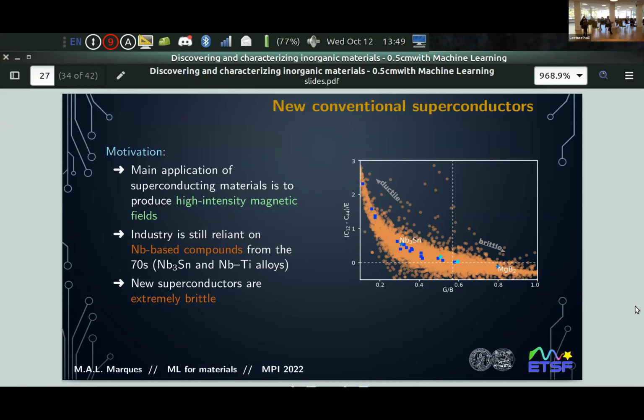Yeah? So if you think that fusion is the future, we have a problem, right? We need superconductors. And we don't care about room temperature. If you are at 20 Kelvin, it's already not too bad. So we embarked last year on an endeavor to try to find an intermetallic superconductor that is not worse, let's put it like that, than the niobium-based superconductors, but that is not brittle. That's the idea. So this is just a plot of the elastic constants. Brittle behavior is here. Ductile behavior is here. So you see niobium-3 tin, that is already quite brittle for technology, is here. Magnesium diboride is there. That's why you don't see any NMR machine done with magnesium diboride. Okay, so it's as simple as that.